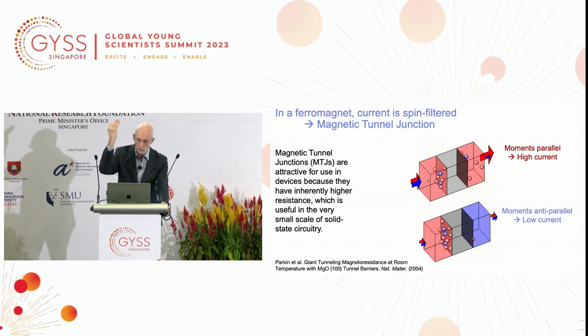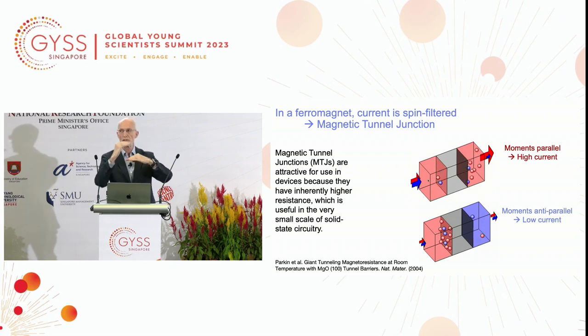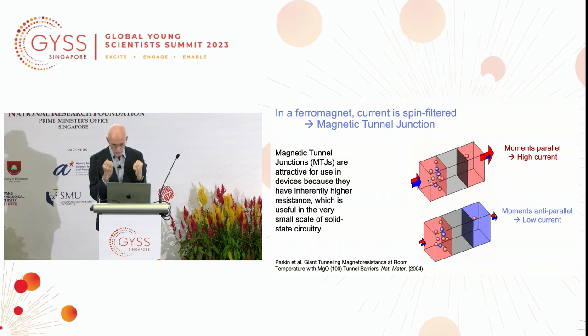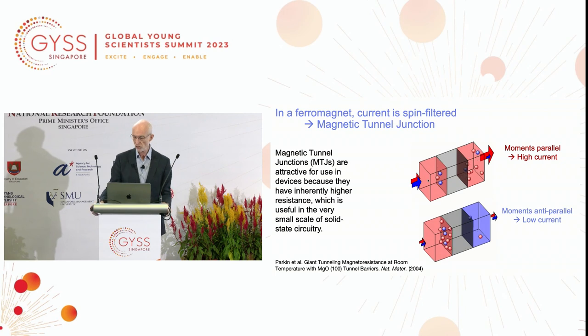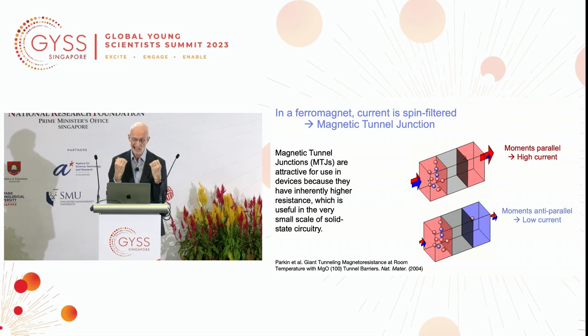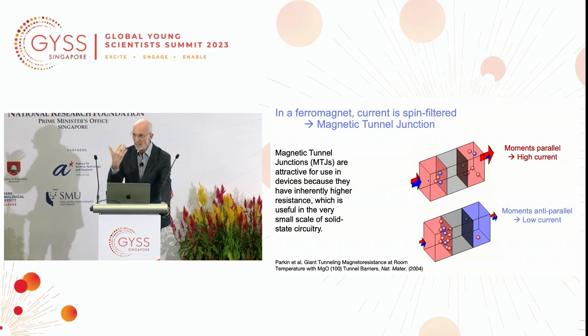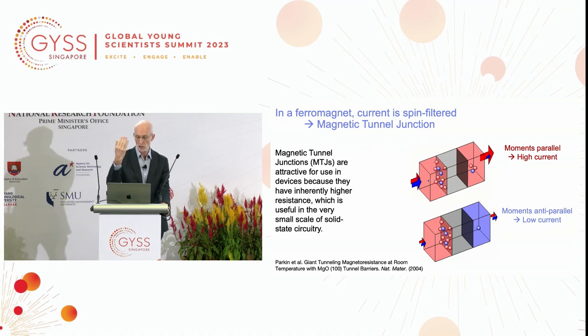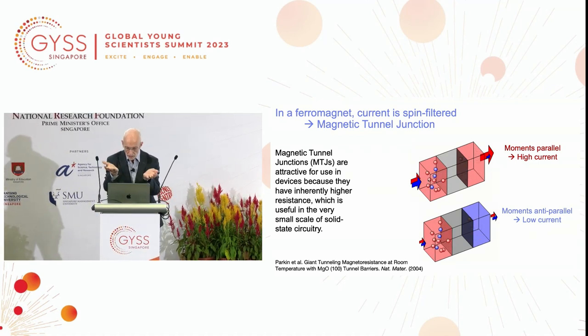The reason is, when you extract current from the surface of a ferromagnet, there are different numbers of electrons with spin up and spin down. They tunnel at different rates, and when the two magnetic layers are parallel, the electrons can tunnel readily of one spin polarization. You switch the orientation of that one layer to the blue direction, and you essentially turn off the current, because there are no available empty electronic states into which those spin polarized electrons can tunnel, because the spin is preserved during that process. So this type of structure can give rise at room temperature to changes in resistance, when you change the orientation of these two layers, of up to several 100%.